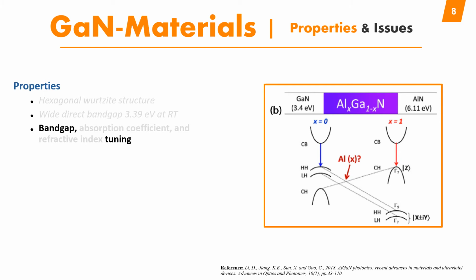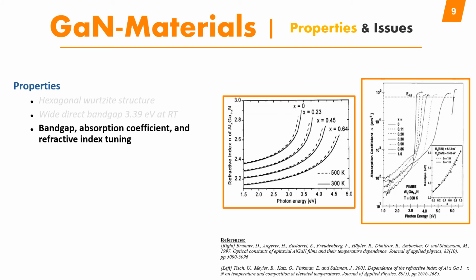Consequently, the absorption coefficient and refractive index can also be tuned by changing the band gap, because there is a direct dependence between these. As we can see from these figures, the refractive index changes with changing aluminum concentration, and also with changing photon energy, which represents the band gap, and the absorption coefficient also increases. Here it is very sharp in the UV region, and you can see that it is tuned to lower UV wavelengths with changing the band gap of the material.